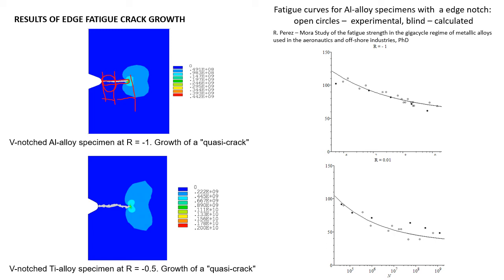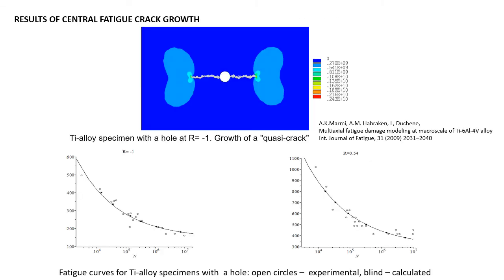The same procedure was realized for another stress ratio, R 0.5, and we can see a similarly good match of the experimental and numerical data. The results of damage function calculation for the specimen with a central hole subjected to cyclic loading are presented on this slide. The experimental data were taken from the paper of Marmi and Duchene, multi-axial fatigue damage modeling at macro scale of titanium alloy. As we can see, the results of numerical simulation and experimental data are in good agreement, similar to the previous case of the edge-notch specimen.